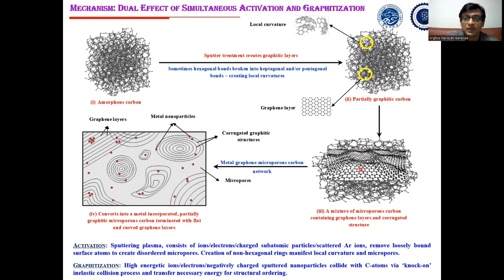And finally, it creates some long-range graphene layers inside this microporous carbon network. And finally, this is creating this metal incorporated partially graphitic microporous carbon terminated with some flat curved graphene layers. So therefore, the dual effect is activation and graphitization. Activation is done by the sputtering plasma, which consists of ions, electrons, charged subatomic particles of argon ions, which remove some loosely bound surface atoms to create disordered micropores.